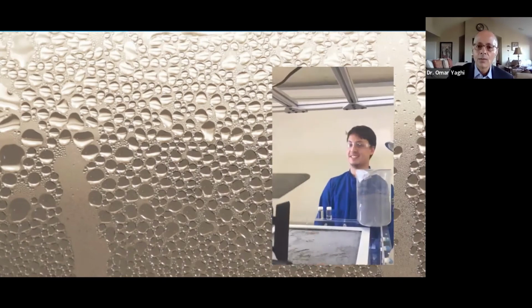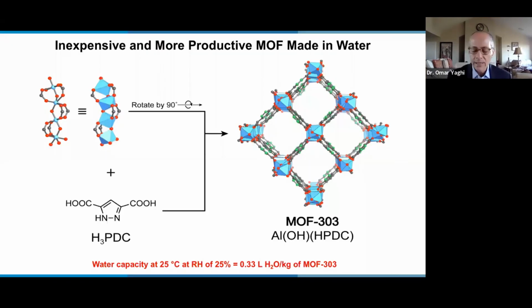Okay, very good. So we wanted to go on. That MOF was a zirconium MOF, and zirconium is rather expensive. So based on our knowledge of how the MOFs behave, we can now use reticular chemistry to make an aluminum MOF. Aluminum is really dirt cheap. And we combined it with this organic linker to make a new porous structure. We call it MOF-303. That works even better than the MOF I just showed you.